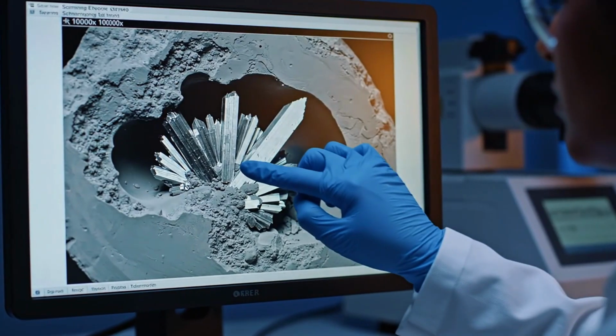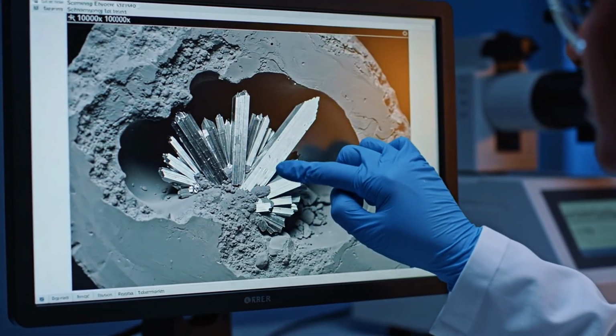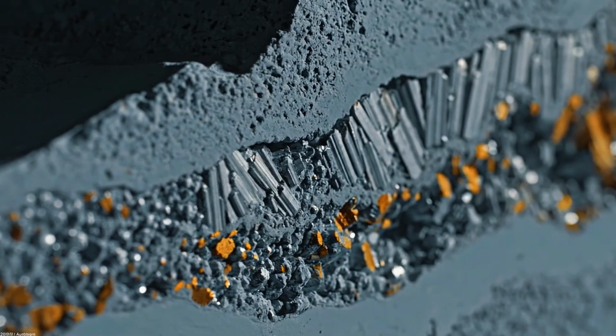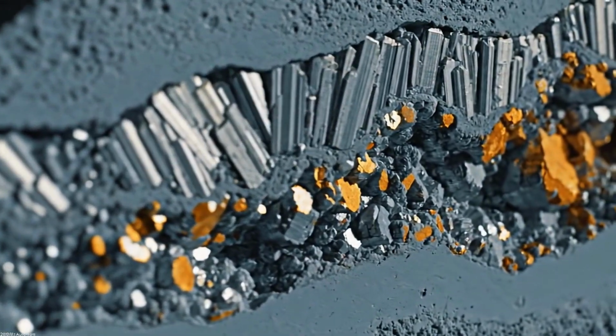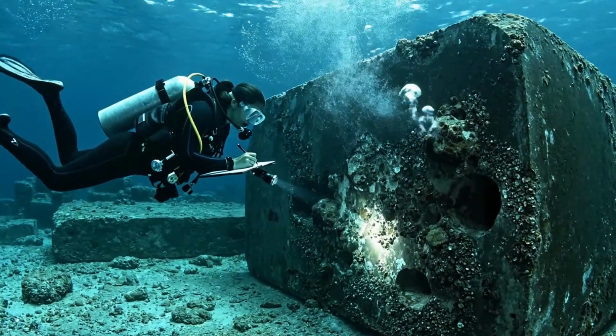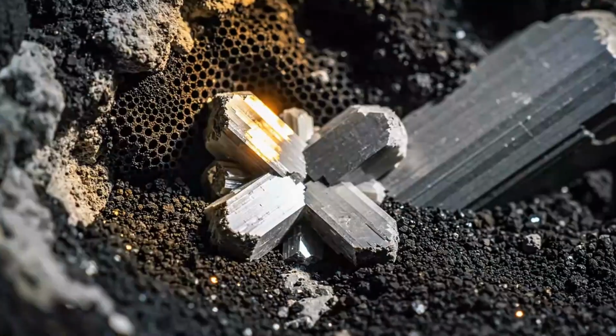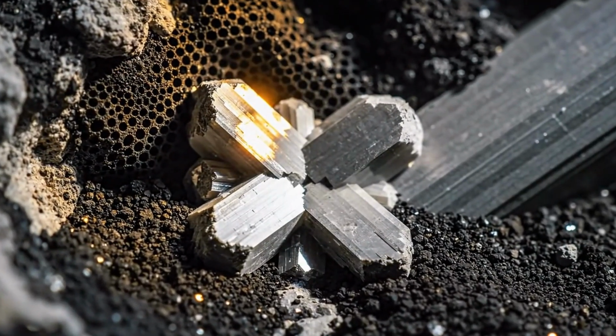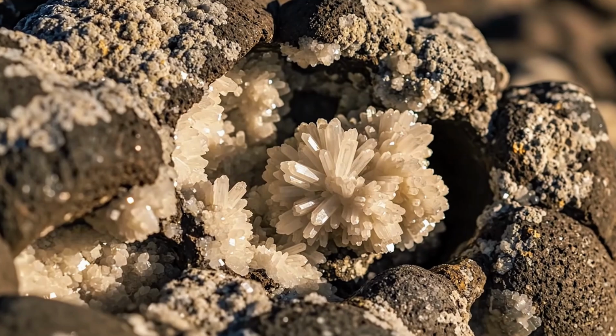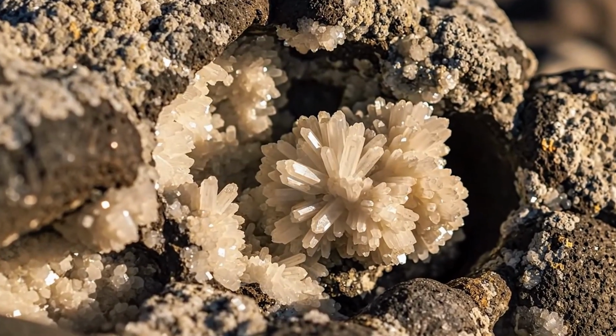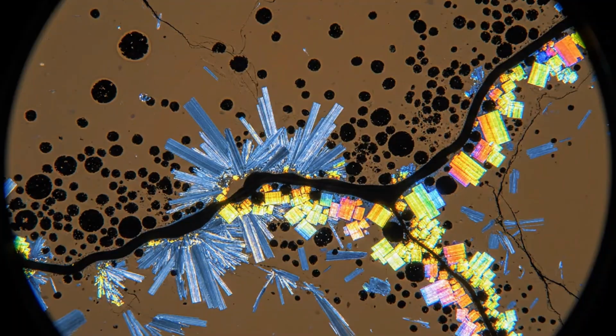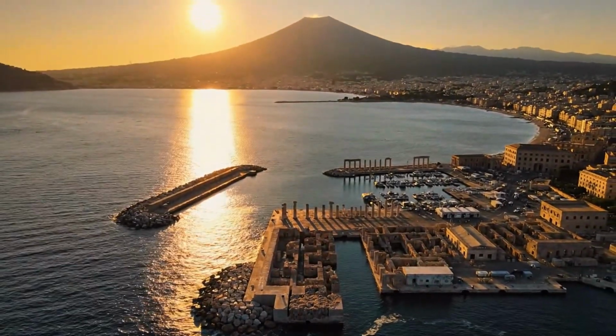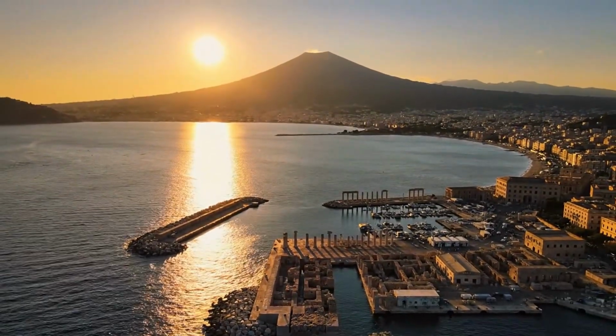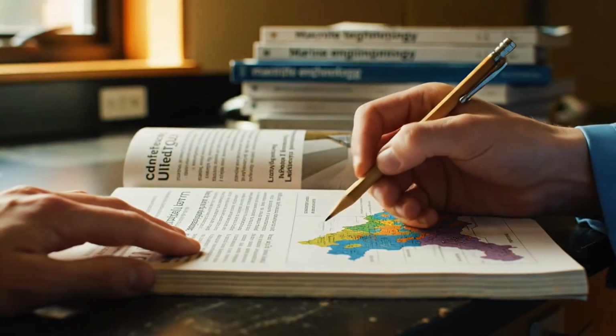They found aluminum tobermorite crystals growing within the cement matrix, crystals that couldn't have formed during the initial mixing and hardening process. These had grown over centuries of exposure to seawater. They also found philipsite, another zeolite mineral, which forms when volcanic ash reacts with seawater over long timescales. And critically, they found that these minerals were concentrated in areas where the concrete had cracked. The cracks hadn't weakened the structure. They'd become reinforcement zones.